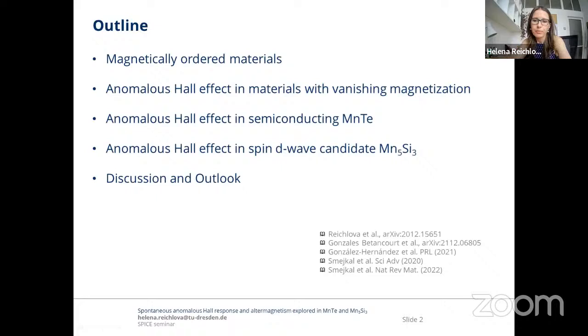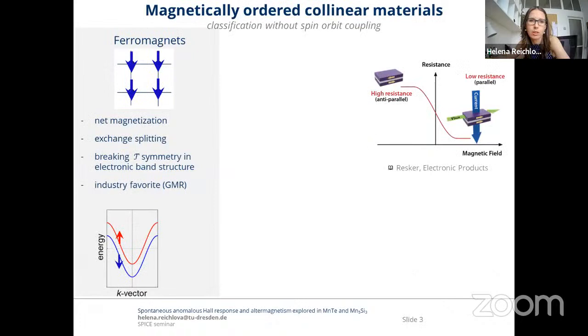So magnetically ordered materials, first thing which comes to our mind are probably the ferromagnets, where the spins are ordered parallel to each other, and therefore they exhibit net magnetization to outside. The second characteristic feature of ferromagnets is the exchange splitting in the electronic bands. The spin up and spin down have in the simple ferromagnet isotropic splitting. And the time reversal symmetry is broken in the band structure, which means that the energy of opposite k vector and opposite spin is not equal.